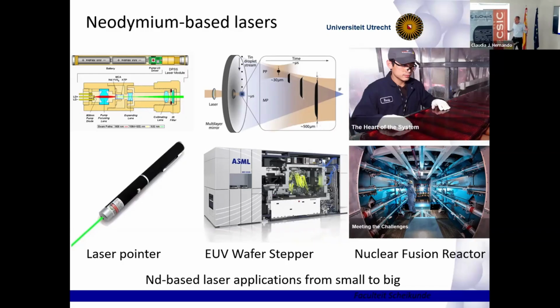But also neodymium YAG lasers are used by ASML in their EUV wafer steppers to produce extreme UV radiation at 13.5 nanometers. They hit the tin droplets with the first pulse of the laser, then the second pulse excites the tin atoms to high excited states, and then they go back to the ground state, emitting 13.5 nanometer extreme UV radiation. So the neodymium YAG lasers are in the wafer steppers of ASML. And even larger scale neodymium glass lasers are used in the nuclear fusion reactor. Hopefully it will at some point produce energy in the future in California. And there are many more applications of lanthanide-doped lasers.